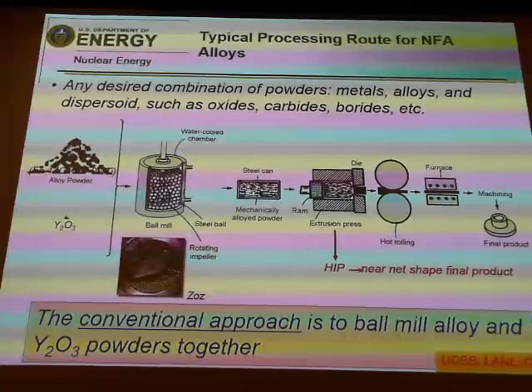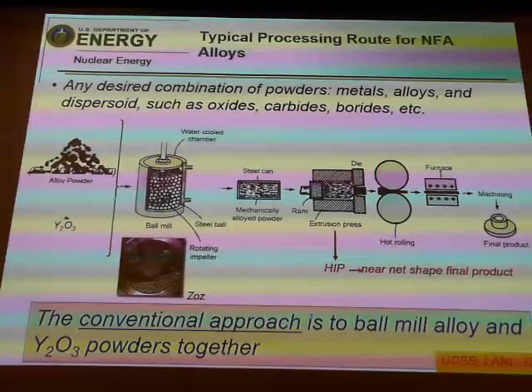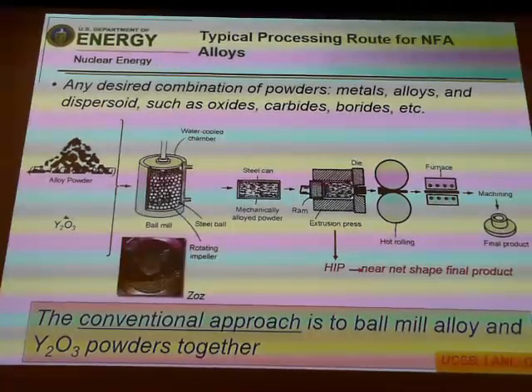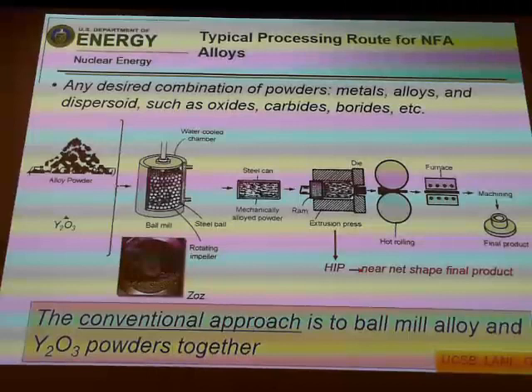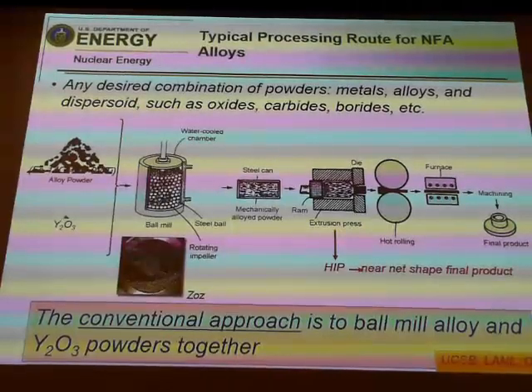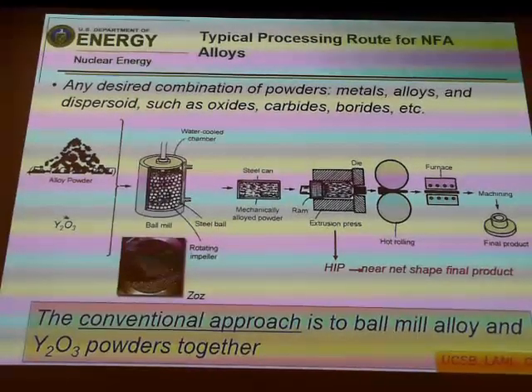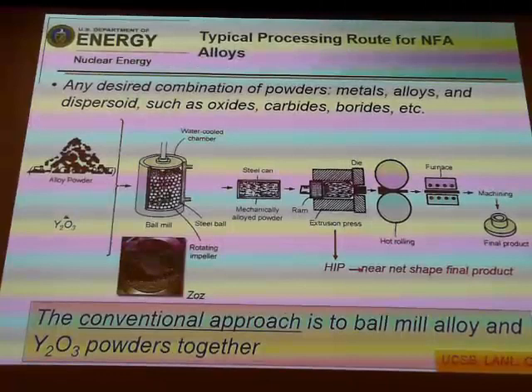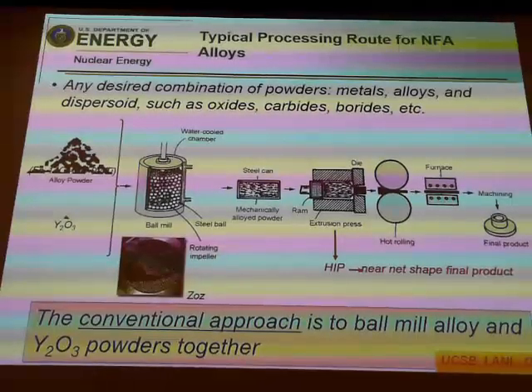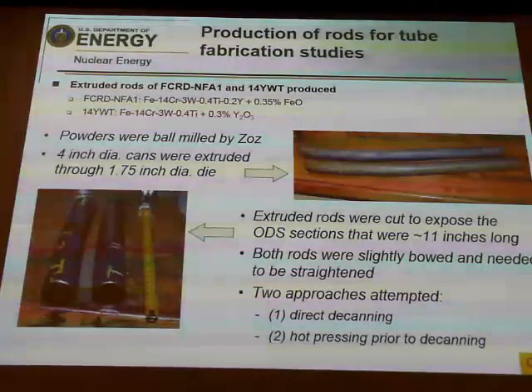And now you get a very fine dispersion of 2 nanometer oxides within the material, which is great. But now you have to try and extrude that into an engineering shape, which, being a high strength material that it is, is very difficult to do all the final machining, the final extrusion processing properties on these materials. So we're making some progress, but we're not there yet.